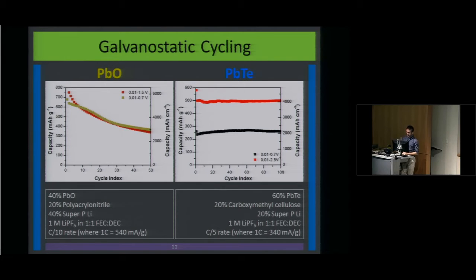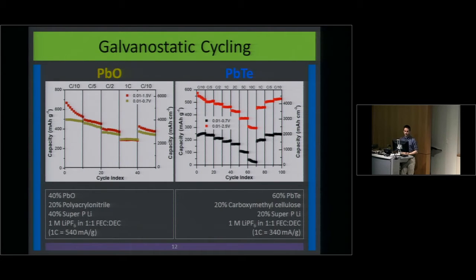So now if we want to try it at a little bit higher rate, we can push them to see the limits of how fast they can be charged. For the lead oxide, we went up to a maximum rate of 1C, charging in 1 hour, discharging in 1 hour. You can see there's capacity fade through all the different C rates. It flattens out a little bit at 1C, but once you return to the slow rate at C over 10, there's capacity fade yet again.